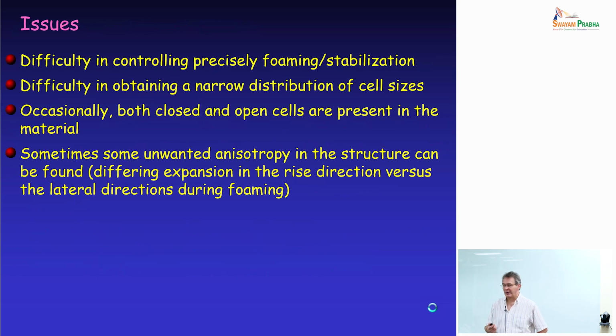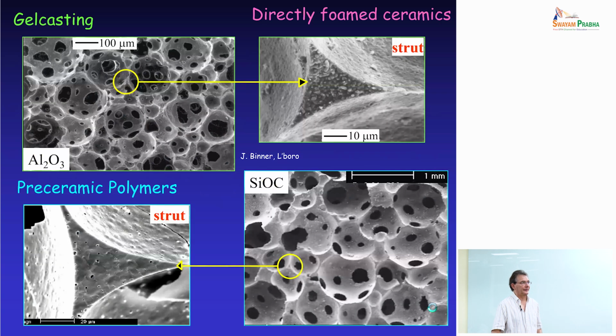There are also issues. One is the difficulty in controlling precisely the foaming and the stabilization of the foam. You certainly have difficulties in obtaining a narrow distribution of cell sizes. Often, occasionally, but I would say often, you have both closed and open cells in the final material. And sometimes, since you're foaming, you're rising your liquid in one specific direction, in some cases you have anisotropy because the cells are not round, but they are stretched in one direction.